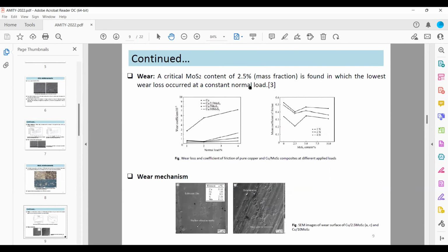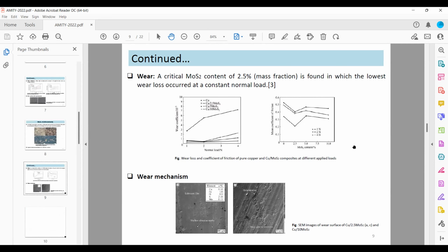Now both the coefficient of friction and wear loss are decreased at all the applied normal loads. However, a high content of MoS2 contributes to the reduction of wear resistance due to reduced hardness of the material. Now in the wear mechanism, when MoS2 is present at 2%, we can see that the lubricating film is present and there are shallow abrasive marks. But at higher percentages of MoS2, delamination occurs because the soft particles of MoS2 are present in larger amounts.